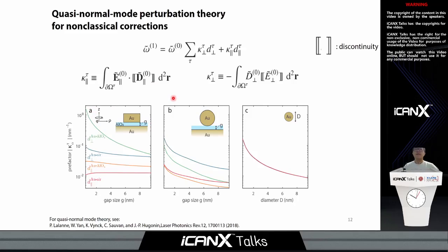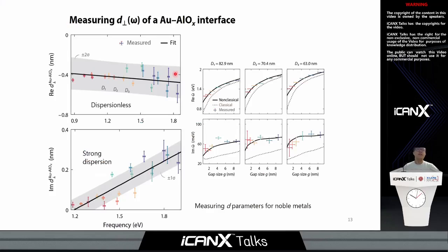So we're able to measure these d parameters, extract the real part and imaginary part of the d parameters, and obtain their dispersion. We see that the real part of the d parameter is dispersionless, while the imaginary part of the d parameter is strongly dispersive. This strong dispersion corresponds to the reason why we see the breakdown of the classical broadening at the smallest gap of our structure, where the broadening is not the maximum. This measurement is particularly meaningful because the theoretical calculation of the d parameter for noble metals is very challenging.